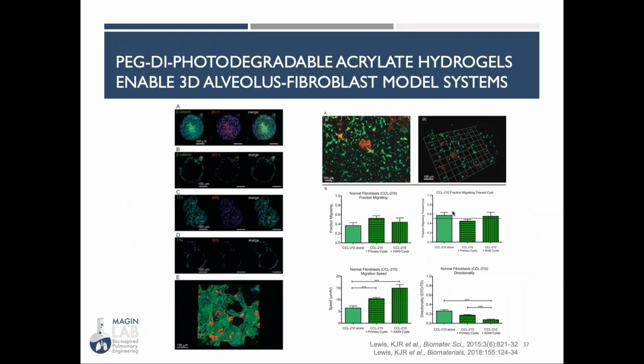One of the really cool studies that has used PEG to look at lung structure came out of the Anseth research group. So they created photodegradable PEG hydrogels that were in the shape of microspheres. You can see they were here. They've surrounded them with epithelial cells, and then once you shine light on these materials, the PEG inside the alveolar-like structure goes away, it degrades, and you're left with something that looks kind of like a lung. This is really exciting. They're showing here labeling T1 alpha, those type 1 epithelial cells, and surfactant protein C, the type 2 cells. So they're starting to get a mix that is a similar ratio to what you see in your lungs.